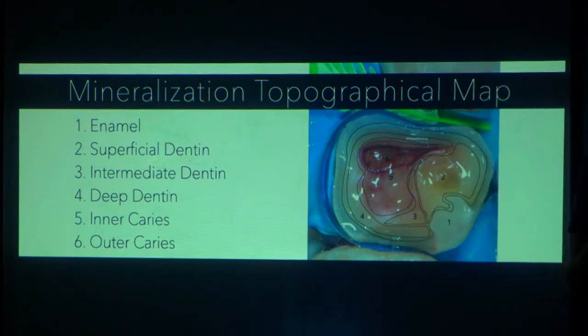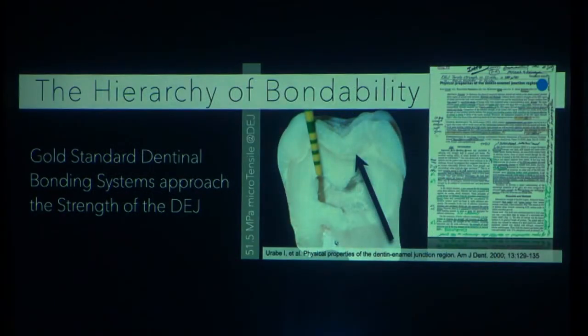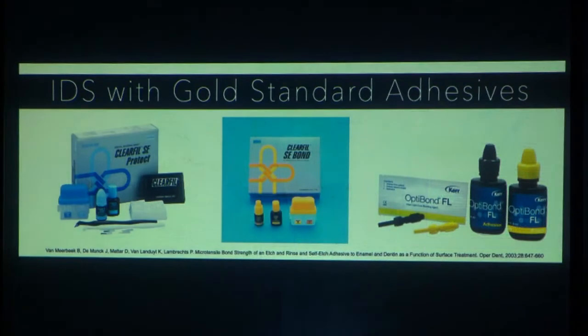Okay, so now let's move a little bit more into what we're talking about. These gold standard bonding systems have the ability to mimic the strength of the DEJ. And the strength of the DEJ was established in 2000 from TMDU, and it was around 50 megapascals. And they made the conclusion that if you can get a bonding system to get on a flat surface about 50 or 40, we're so close to the cohesive strength of enamel and dentin, why are we even worried about retention form or resistance form? There need to be new principles of adhesive dentistry.